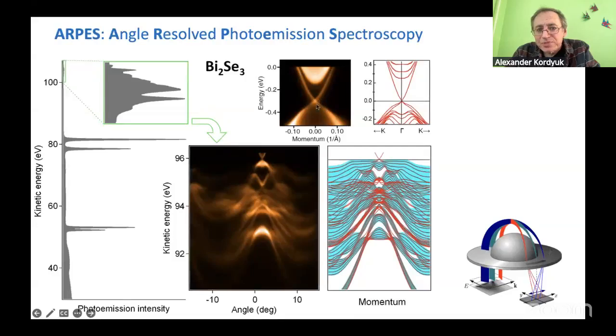You see. In experiment, it is here, but here it's already mixed with the bulk state, because in experiment it is more or less a three-dimensional compound. It is quasi two-dimensional, but these bands have kz dispersion. And if you have kz dispersion, you have not one band, but for different kz different bands, because you have the small escape depth of electrons. Escape depth of electrons is a few layers. And this few layers, due to the uncertainty principle, means that you integrate in reciprocal space. If it is two layers, you integrate roughly half of the Brillouin zone in kz.